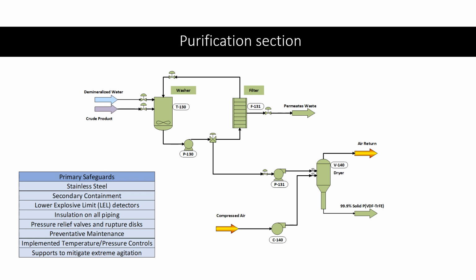The mixture will then be transported to an ultrafiltration membrane to separate the dissolved impurities, along with a considerable amount of DI water, as the permeate fluid, and the pure product will remain in the retentate, which will flow back to the washer tank with a fresh batch of DI water. This process will have 7 washing cycles to obtain a 99.9% pure PVDF-TrFE polymer. In every wash, the permeate will be sent to a qualified treatment plant to properly remove these hazardous chemicals, and the system is maintained at a steady state by feeding the washer tank an equal volume of the permeate exiting the diafiltration.